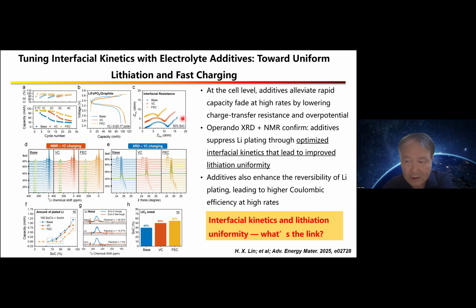So with our results of operando XRD and NMR, we confirm the additive suppresses lithium plating through optimized interfacial kinetics, which leads to more uniform lithiation.